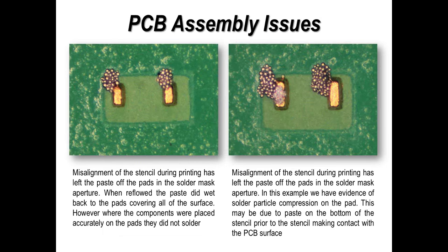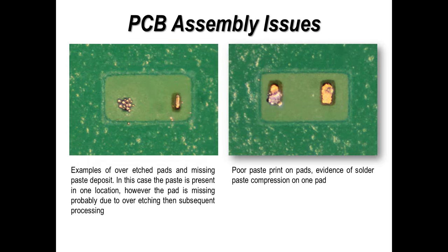And in this example, we can see misplacement, but also on the right hand side, we can see some measure of coining of the solder paste, where the solder paste particles are compressed between the stencil and the pad. And this is probably due to paste being present on the stencil prior to the printing operation. So from a previous print, we've got some paste trapped underneath the stencil. And as the stencil comes down to the board, the particles are compressed onto the pad, and you get this, what some people refer to as a solder particle splat, or coining, or compression.